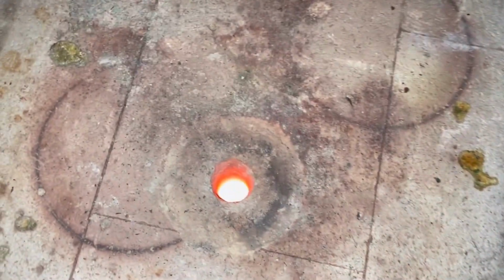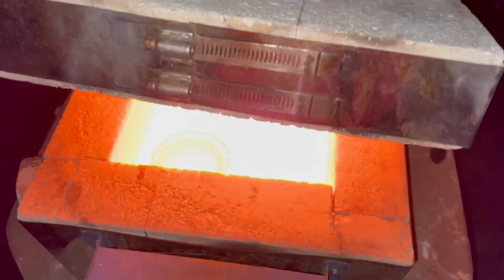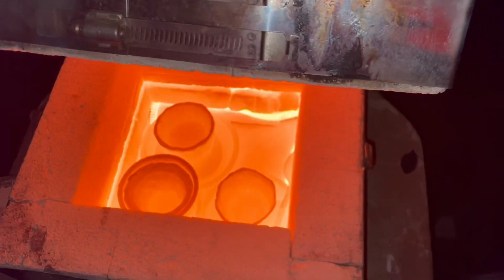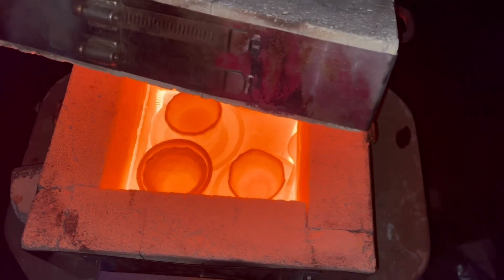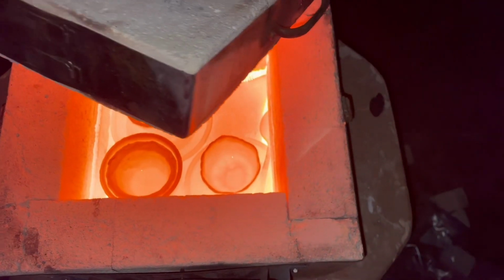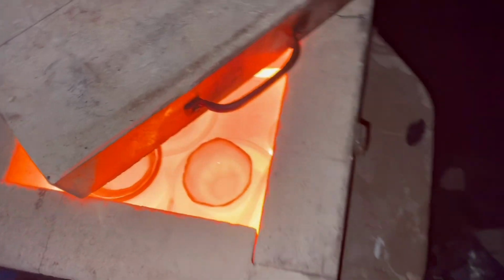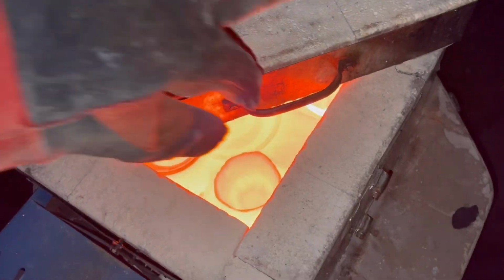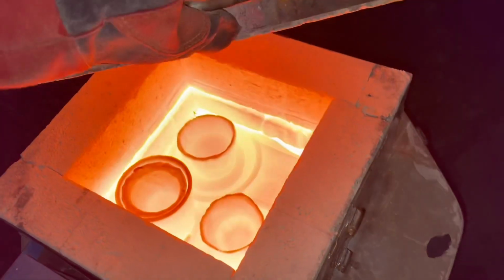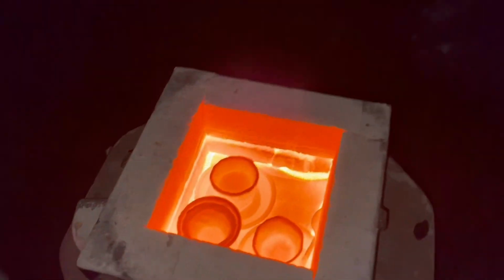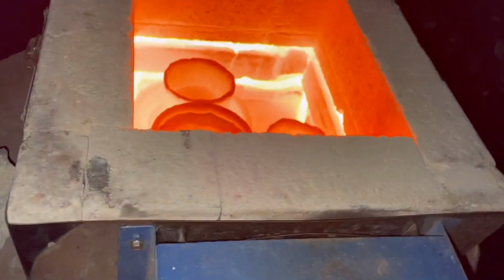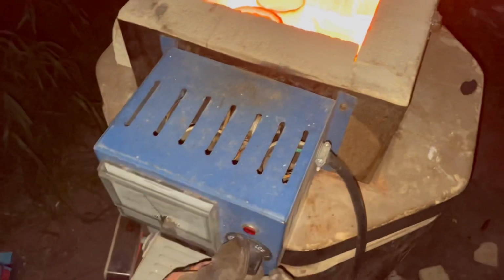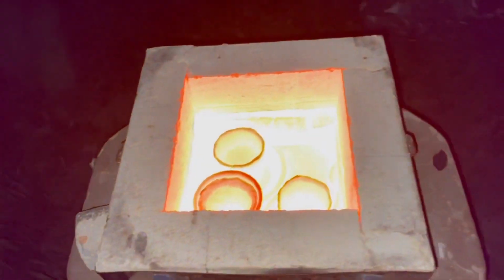The furnace has reached a temperature in excess of 1800 Fahrenheit, or 1000 Celsius. The crucibles are no longer bubbling. There's no pieces of metal floating on top or anything. It just looks like little cups full of honey. So that means that this is done. I'll just open the top of the furnace, shut it off, let everything cool.